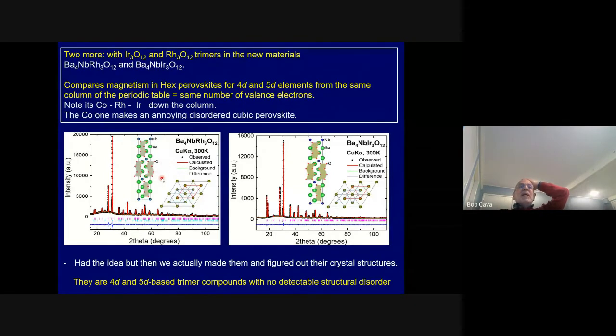Now, unfortunately, cobalt, which we all know is interesting from what I showed you before, doesn't work. It makes a cubic perovskite. Cubic perovskites were fun for some other reason, but in this case, I didn't like it. So the competing phase here would be a perovskite. What we're looking for now is something that has face-sharing octahedra, to show that we get delocalization of the spin in a trimer, and then separation of these from each other by putting a non-magnetic atom in between. We can do it with rhodium and iridium. We just can't do it with cobalt. But let's see what happens.